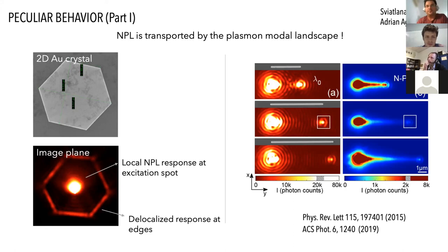You're absolutely right. I agree, it's a very good suggestion. Because it's true that these hot electrons will have some kind of diffusion mechanism, and maybe we could probe the diffusion lengths of this hot electron mechanism through a measurement. If you do a pump-probe, that could be beautiful. Absolutely. Nick Van Hulst did it through transient reflectivity, but absolutely, with the PL, the correlation would be interesting.